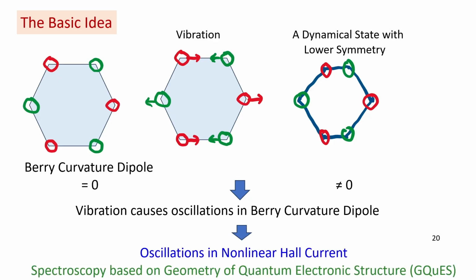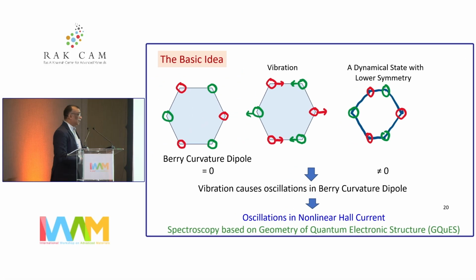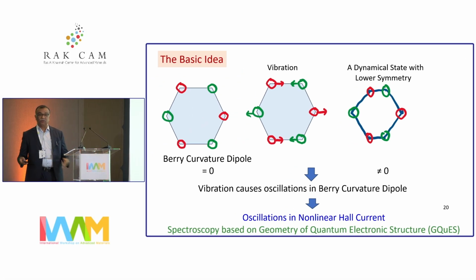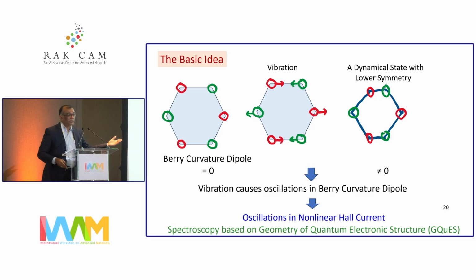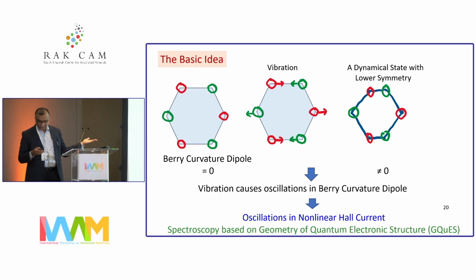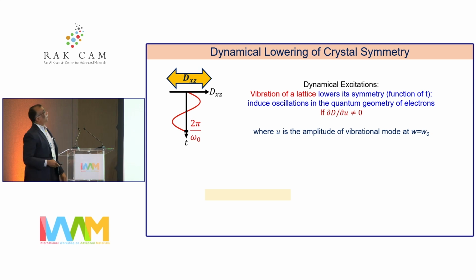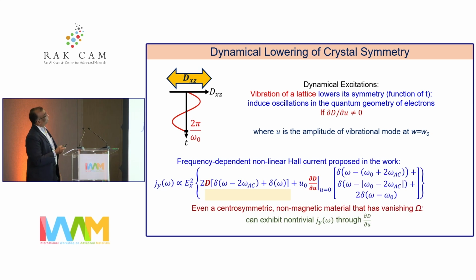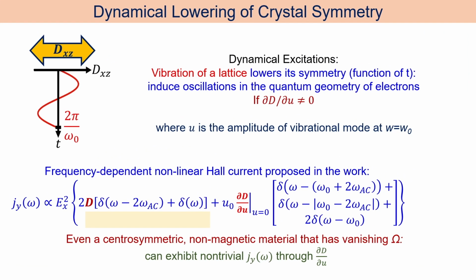Based on that, we said there should be oscillations in the nonlinear Hall signal, and based on that, we proposed a new spectroscopy. If you measure oscillations in the nonlinear Hall signal, you will be able to tell the vibrational frequency of the system. So that's the new spectroscopy that we propose. The idea is that the crystal symmetry is lowered by dynamical oscillation of the lattice, in this case vibration, and if the amplitude of vibration is u, it induces an oscillating Berry curvature dipole with a period given by the vibrational frequency. And the frequency-dependent nonlinear Hall current has two components.